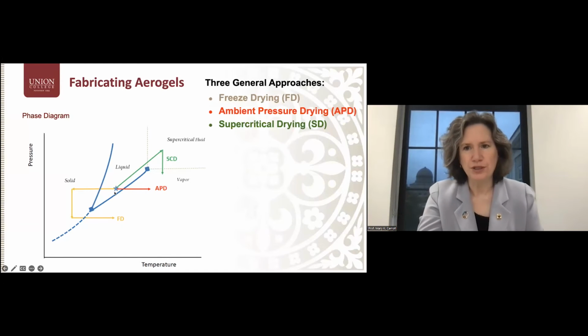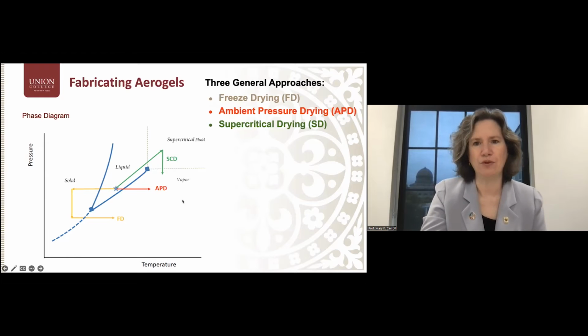And the other option, which is the most common way of making them, is to use some sort of pressure vessel and take the temperature and pressure of the wet gel above the supercritical point of the liquid mixture that's in the pores. If we're in this region, the pores are filled not with liquid, but with supercritical fluid. If one then releases the pressure, the fluid escapes without causing pore collapse, and the material can then be cooled down, and lowered the pressure and cooled down, and one is left with aerogels.